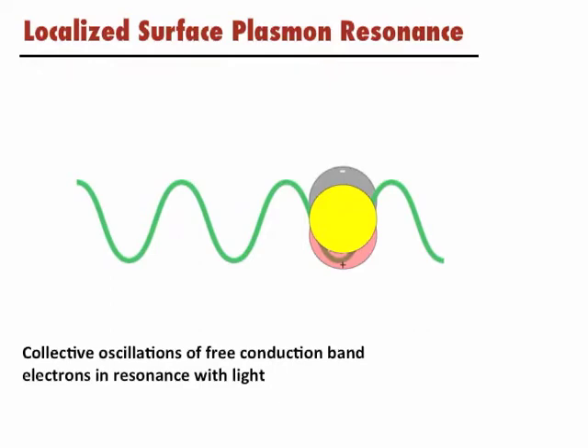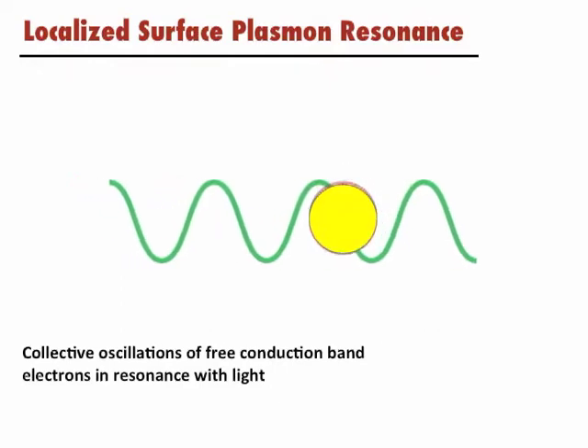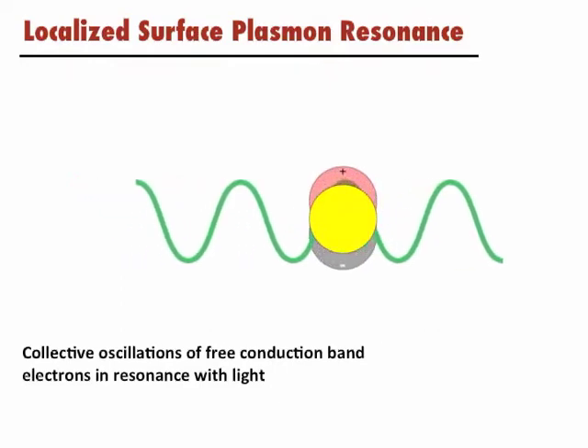When the second half cycle of light passes through the particle, this electrostatic distribution is inverted, resulting in a large field gradient. The plasmon coherence is short-lived, about 15 femtoseconds, and is very sensitive to the surrounding dielectric. As a result, plasmonic nanoparticles can function as transducers capable of detecting dielectric changes at the nanoparticle surroundings interface.